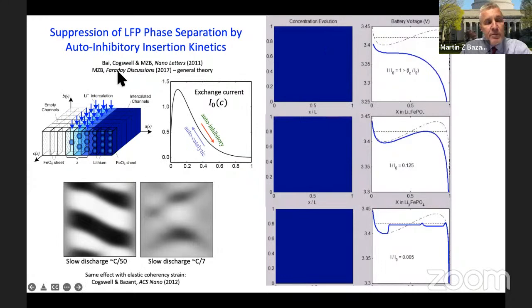And in fact, my paper Faraday Discussions 2017 goes into great detail on the general theory of this phenomenon. If you're interested, I summarize here where it comes from. In this model, the reaction rate versus composition has a prefactor that is concentration dependent. So it's autoinhibitory, or decreasing, during insertion, and it's autocatalytic, or self-accelerating, during extraction. And that behavior leads to growth or suppression of instabilities leading to concentration changes.